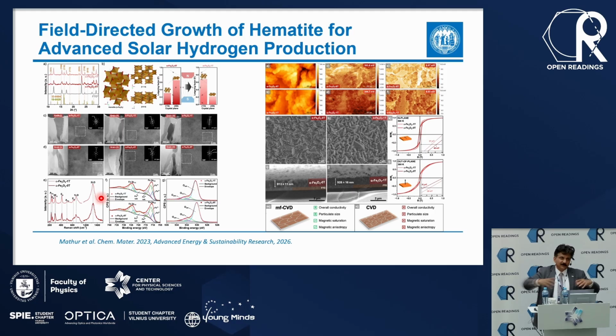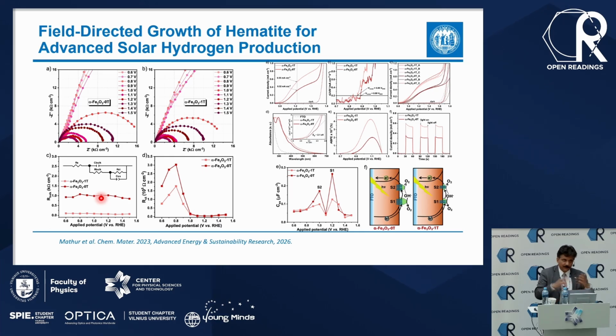Larger domains mean the volume fraction is decreasing, so you have less grain boundary resistance. We did this with impedance spectroscopy, and these studies tell you the number of inactive states, because on a catalyst surface you can imagine there are like stools. These are the sites where molecules can come and sit down and be activated. So these states are not all active. Some are active, some are not active. And these can also be changed.